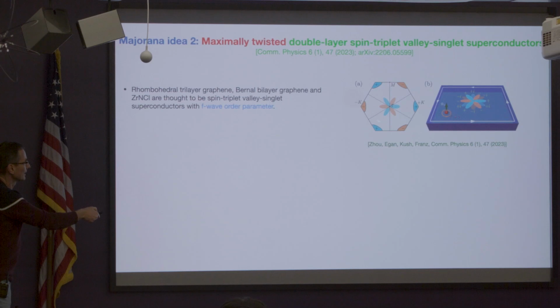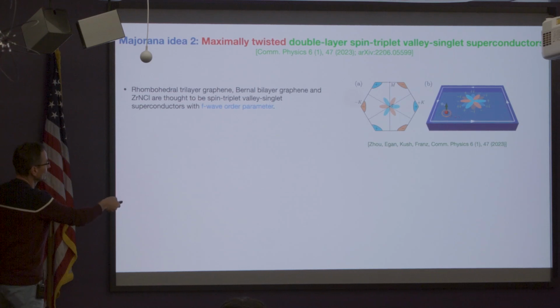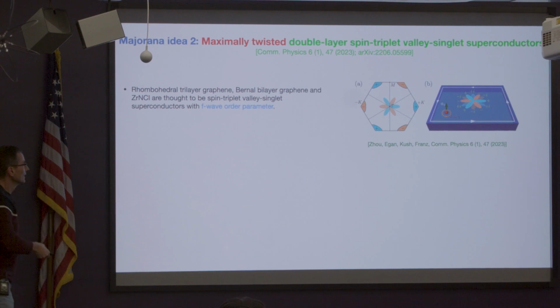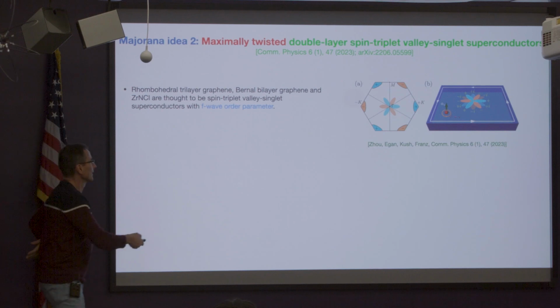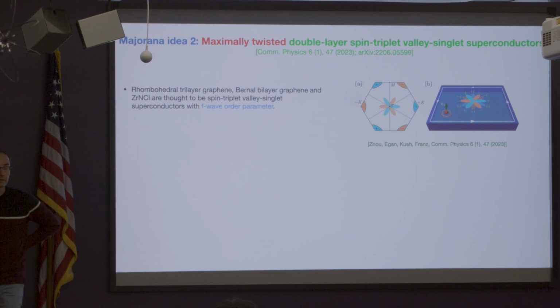What you see here in the middle, that's a representation of that F-wave order parameter. It vanishes along these 3 lines, and it's maximal along these lobes, and always, of course, changes sign upon 60-degree rotation. So the conjecture is, again, that these materials have this type of superconducting ground state somewhere in the part of their phase diagram.